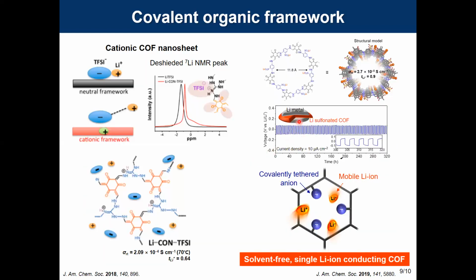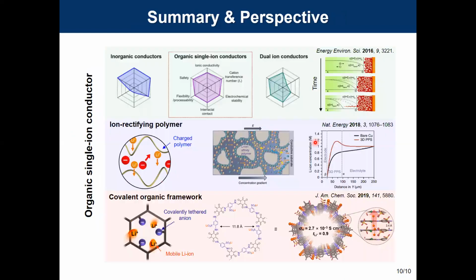So the unusual ion transference phenomenon of that COF allows reversible lithium plating and stripping on the lithium metal electrode, demonstrating its potential use for lithium metal batteries.